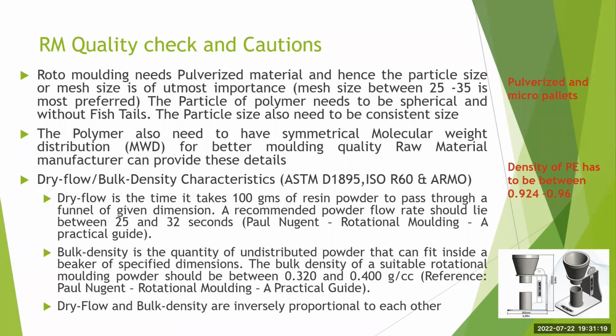Another very important characteristic is dry flow and bulk density. Very, very important. And there's a standard available, ASTM, ISO, and ARMO, the American Roto Moulding Association standard, which gives a direction on what the quality of dry flow and bulk density should be. Your dry flow needs to be 25 to 32 seconds, and your bulk density has to be from 0.32 to 0.4 grams per cc. So it is very important that these properties are checked when you are getting the pulverized material from the outsource partner, or if you are pulverizing it yourself. It's very important.